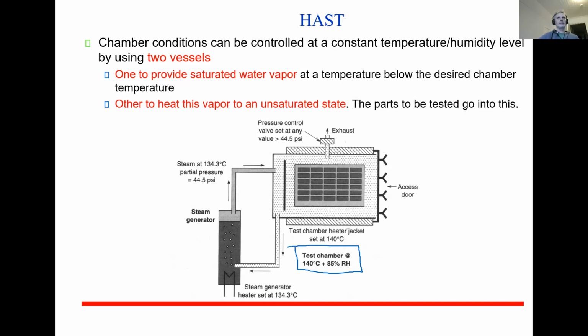Now we just need to remember that relative humidity is a function of temperature. So you need to have a certain absolute humidity, and then you play with the temperature, and then you can have the relative humidity. So how this system operates is that first we have a steam generator. Basically we form saturated water steam, meaning that in this case the temperature of that steam is 134.3 degrees centigrade. So the relative humidity is 100%. And we inlet that saturated steam into the testing chamber here and heat it up.